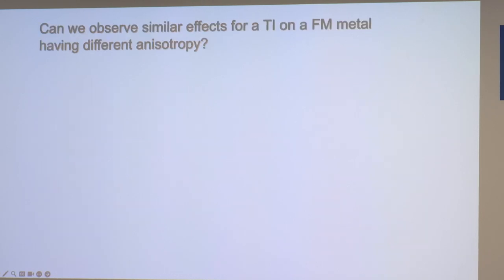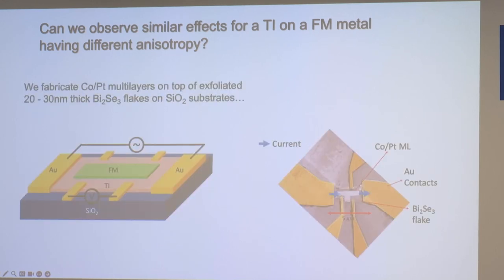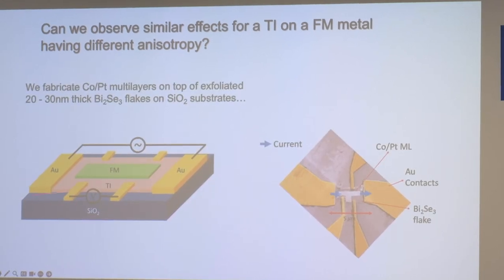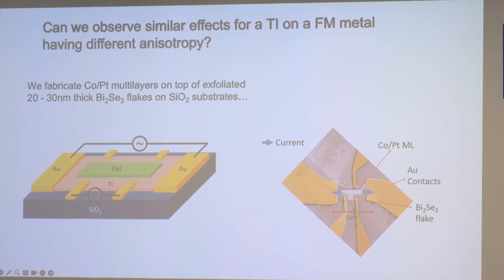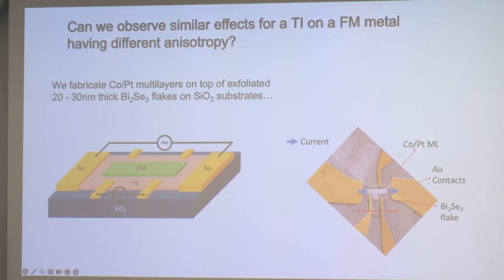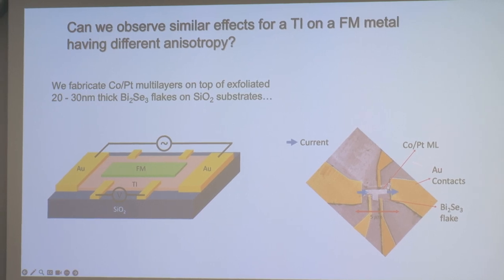Okay. So I'm just going to say a little bit more about trying to do this again on a ferromagnetic metal. Here we are talking about doing something on a magnetic insulator, but if you want to have a real spin torque device, you have to look at the coupling with a ferromagnetic metal and a topological material. And so we basically tried to do a very similar thing with bismuth selenide on top of silicon oxide, which was gated, and then having cobalt platinum multilayers on top.